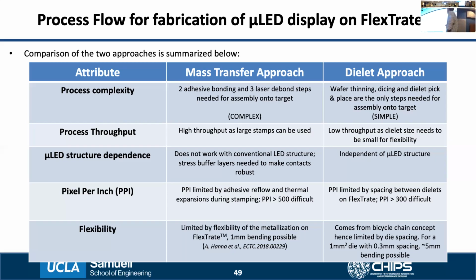Actually, I have not included that as part of this, but my colleague Arsalan has done a lot of studies on the reliability of copper interconnects on flex. One thing is we don't directly metallize on the PDMS. We usually have some stress buffer layers. And also the interconnects are usually corrugated, so they are vertically corrugated, and that's to reduce the buckling that is present on the wires.